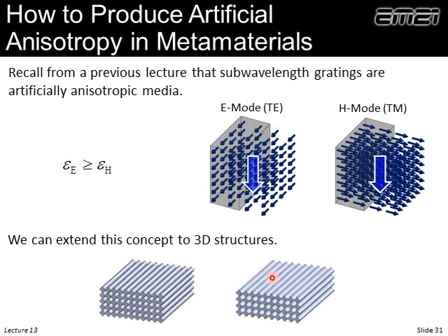Now these two would be uniaxial metamaterials because we have 2 directions with the same dielectric constant. Imagine the electric field oscillating in the vertical direction, and horizontally, it really is seeing the same lattice. However, an electric field oscillating in this direction sees an entirely different lattice and would have a different dielectric constant. So these two have uniaxial symmetry. And in fact, in our research group, this is what we're playing with most, the uniaxial metamaterials.